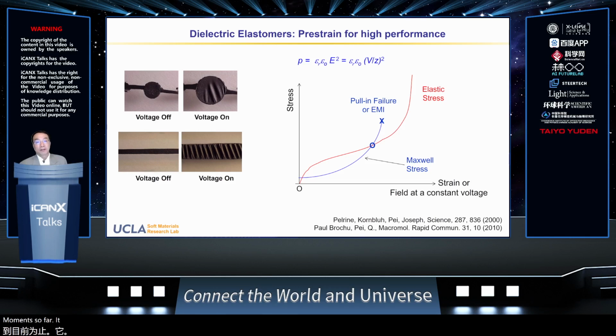So from an experimentalist's viewpoint, I plotted this chart here. The red curve shows the typical stress-strain behavior of a dielectric elastomer. What you see here is a large stress-strain plateau. When a constant voltage is applied, the voltage causes the film to deform, and as you increase the voltage, the strain from the maximum stress increases. But the issue here is that you see the equation showing that the maximum stress is proportional to the square of the electric field.